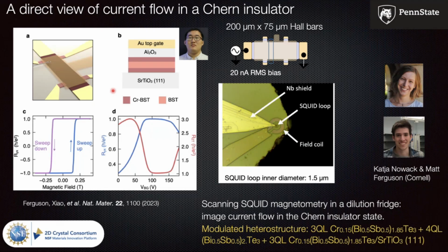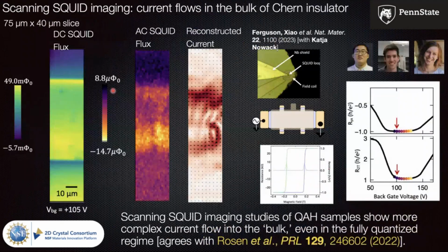And then Katja and her student went looking, and of course the data they found was quite surprising. You can certainly see edge states, but when you are deep in the quantum anomalous Hall quantized regime, what their scanning SQUID shows is that there is current flowing everywhere, and it's complicated. There are swirls of current going into the middle of the sample, and so on. And it was just not what we expected.